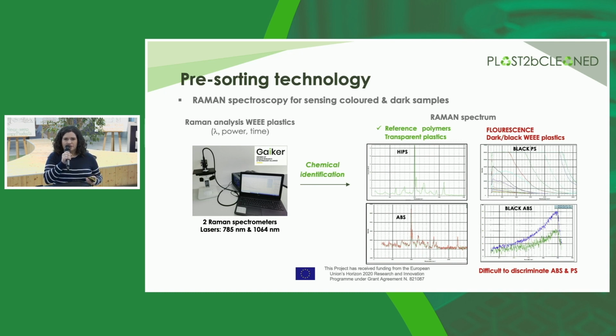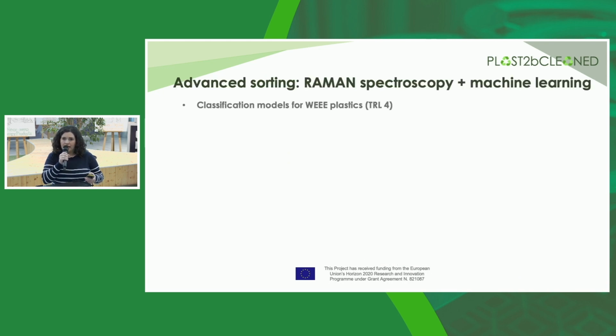The target with the Raman analysis is to obtain a high quality Raman spectrum. If we get that, we can identify a compound chemically. In the pictures on the right, you can see that we obtain clear spectra for reference polymers or transparent or light colored plastics. However, when we analyze the WEEE plastics, we obtain a fluorescence effect. Fluorescence overlaps the characteristic bands of the polymers, so it was very difficult to discriminate the target polymers only with the Raman spectrum. Nevertheless, between both wavelengths, we determined that with the laser of 1064 nanometers, we get less fluorescence in the Raman spectrum of WEEE plastics. So, it was clear that we had to combine Raman spectroscopy with machine learning techniques to